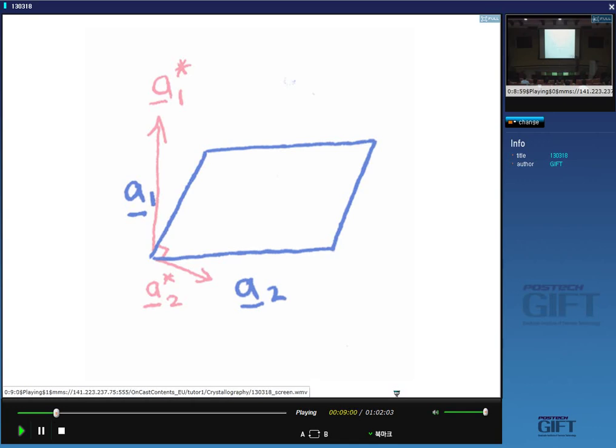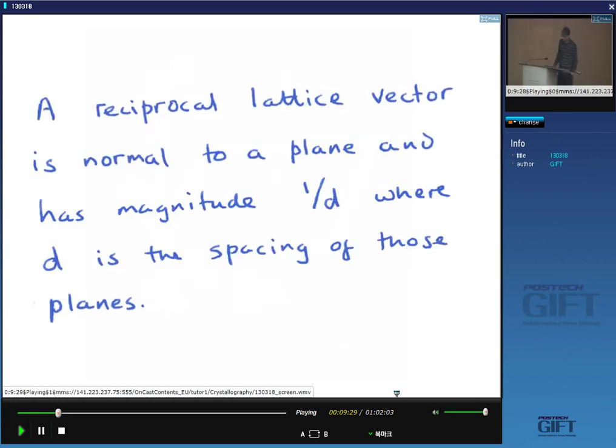Similarly, here I've got an oblique cell where this is A1 and this is A2. A1 star must point at 90 degrees to this plane here, and therefore A1 star is not parallel to A1. And similarly, A2 star must point at 90 degrees to these planes, and therefore it's not parallel to A2. So, just to summarize, a reciprocal lattice vector is normal to a plane, and its magnitude is 1 upon d, where d is the spacing of those planes.